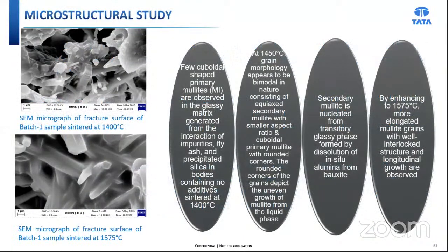Now coming to the microstructure study. Few cuboidal shape primary mullite is observed when the sample is fired without additive at low temperature. With rise in the temperature, the uniform equiaxed secondary mullite is observed, which is uniform and homogeneous in nature. And secondary mullite is basically nucleated from the transitory glassy phase formed by dissolution of in situ alumina from bauxite. With rise in the temperature up to 1575 degrees centigrade, more elongated mullite grains with interlocked structure are observed.